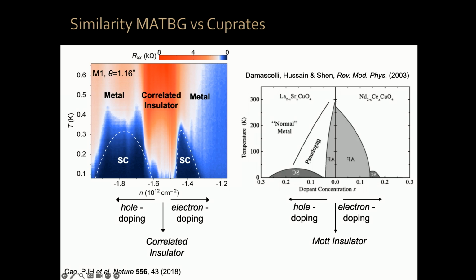In high temperature cuprate superconductors, zero doping means actually 1 electron per unit cell. You have a Mott insulator, a correlated insulator which is a Mott insulator. You add holes and you have a superconducting dome. You add electrons and you have a superconducting dome. For magic angle twisted bilayer graphene, add 2 holes or 2 electrons per moiré unit cell, you have a correlated insulator. You add holes, you get a superconductor. You add electrons, you get a superconductor.